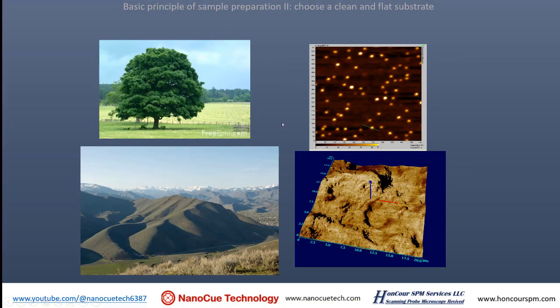Look at the particles in the lower right corner of this image. You don't see a nanoparticle there, and that's because of the scale. It's a 20 micron scan, so you're actually looking at a sample packed with far too many nanoparticles, dried on the surface. Because you don't see individual ones, you zoom out to 20 microns. So you're literally looking at a top view of a mountain and wondering why you don't see the trees. You zoomed out too much, the scan area is too big, your sample is not separated, and the background is not flat. The upper right corner is a very nicely prepared sample that has a flat, clean background.